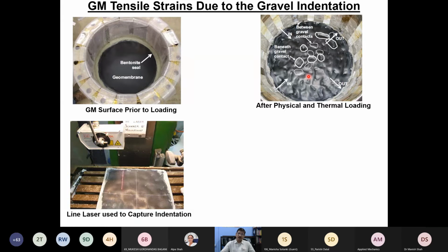So we wanted to really see what happens for the indentation, because the gravel particle is pushing here and the indentation is formed. Suppose we want to measure the strain within the geomembrane, how do we capture that? If I remove the load, because of the elastic rebound, the geomembrane will go back to the original position, or at least rebound a significant portion of the strain.